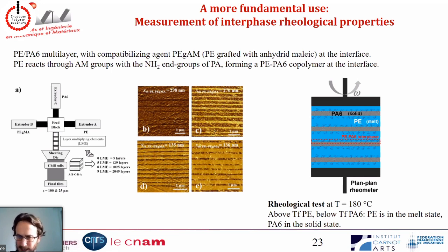So in this study, what we did was make compatibilized films. So it's these compatibilized films I talked about previously. So we made a multi-layer of polyamide 6 and polyethylene. These polymers, they don't like each other at all. So if you just make a multi-layer without anything else, you will have a really large amount of delamination. So you cannot really achieve this multi-layer structure. So what you have to do is add, again, this compatibilizing agent, which is almost always the same in the industry. In this case, it's polyethylene grafted with maleic anhydride. And this polyethylene will react at the interface with the end groups of polyamide and will form a copolymer, PE-g-PA6, that will segregate at the interface. And due to this compatibilizing agent, you will bring some stability to the system, and you can make this really nice multi-layer structure where you control exactly the thickness of each component.